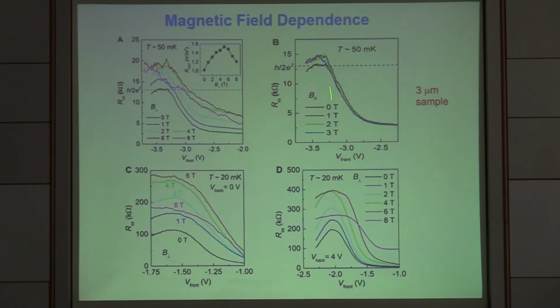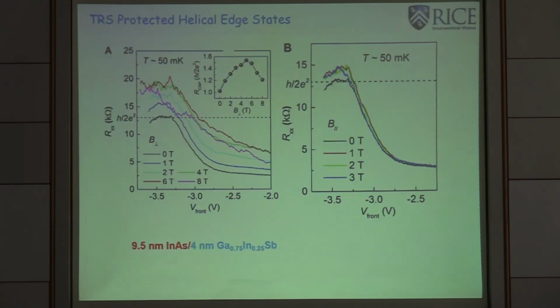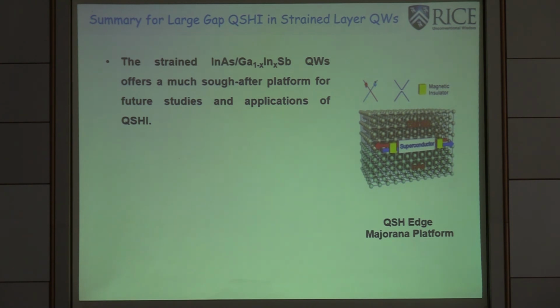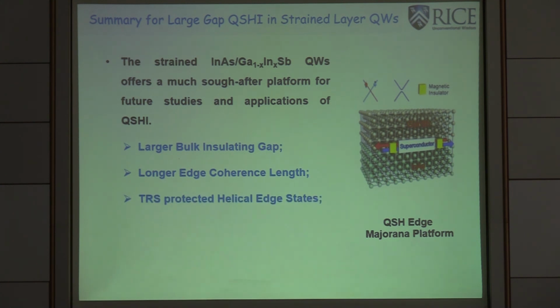The other property is related to magnetic field dependence. I'm not going into detail, but just to say this sample really shows a very sensitive dependence on the magnetic field direction and the magnetic field strength. Therefore, this recovers the single particle picture of the Z2 topological insulator. Because my time is limited, I just show the last transparency. That's the summary. Basically, we can realize a large gap topological insulator with proper edge state properties, which is suitable for making a Majorana platform.